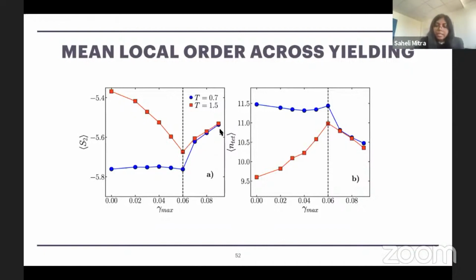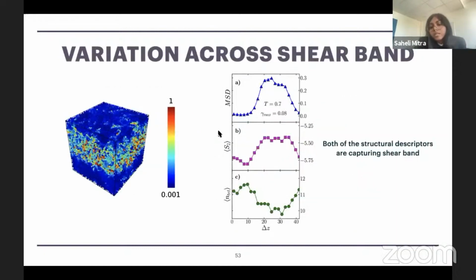Now, above yielding, there appears a shear band in the system. So we wanted to see the variation of our structural order parameters in the presence of a shear band. Like before, we can compute the mean square displacement in the direction perpendicular to the shear band, and we can locate the shear band. We see from both Ntet and S2, for example, that the value of average Ntet is lower in the shear band regime and the average S2 is higher in the shear band regime. That means in the mobile shear band part, the local structural order is actually less compared to the part outside of the shear band. So this again gives the indication that the part inside the shear band and the part outside the shear band have different structural environments.